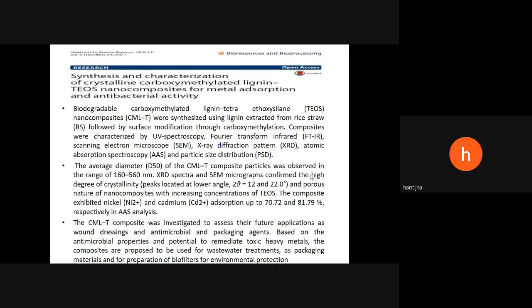Another work was synthesis and characterization of crystalline carboxymethylated lignin nanocomposite for metal adsorption and antibacterial activity, in which we have used the lignin extracted from rice straw, which was then surface modified using carboxymethylation and then combined with the TEOS to form the composite. These composites were then characterized by UV spectroscopy, FTIR, SEM, XRD, AAS. AAS was used for seeing the removal of the metal ion using this composite.